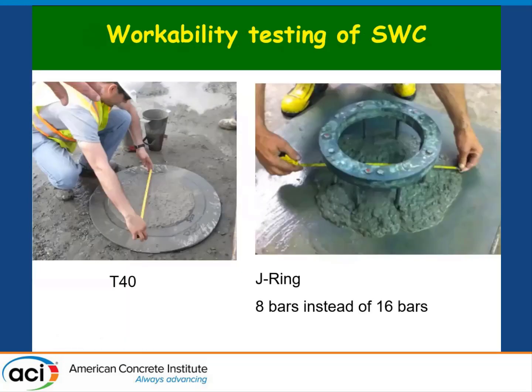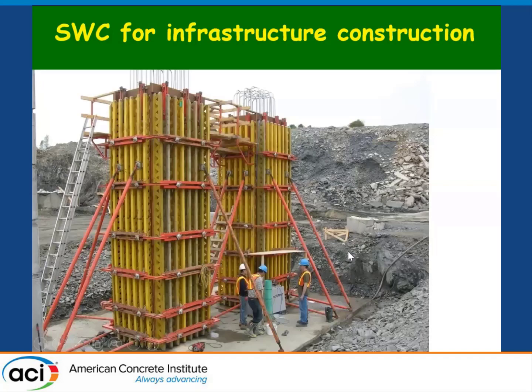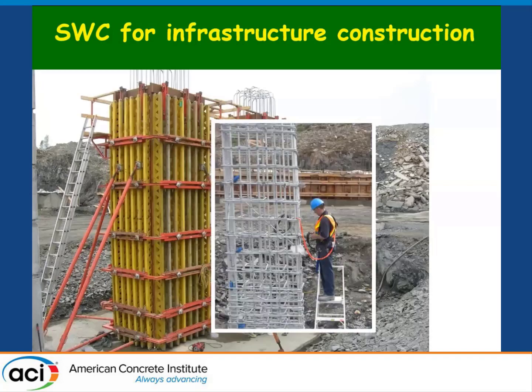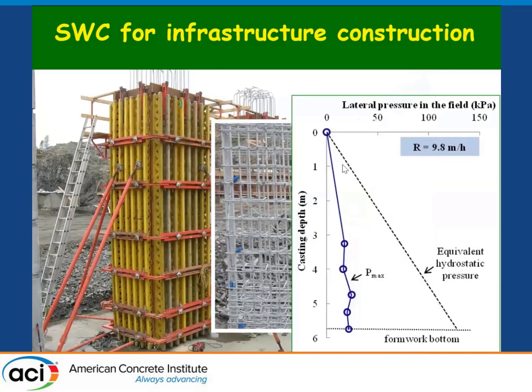The concrete properties were measured using the slump flow, and there you see that measuring the T40 or 40 centimeters, or 16 inches. And then we're using the modified slump flow that I'll talk about a little bit later, that uses, instead of 16 bars, in this case 8 bars. So these concretes were cast from the top and consolidated very lightly. And we also measured the form pressure, and you can see the form pressure is much lower than the full hydrostatic pressure.